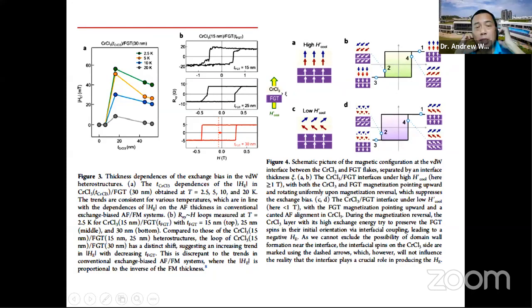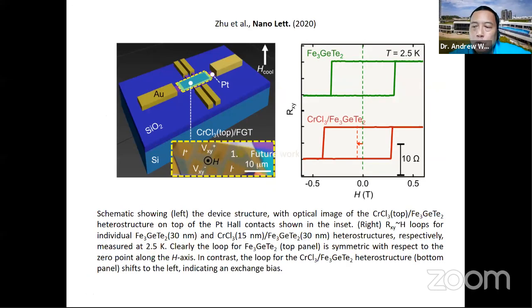So to summarize, we have managed to fabricate a simple antiferromagnetic and ferromagnetic heterointerface device that shows this exchange bias coupling. It's about 50 millitesla. So it's at low temperature, 2.5 K. But nevertheless, it's a step in the direction of using these 2D heterostructures for real devices. So that's our latest work.